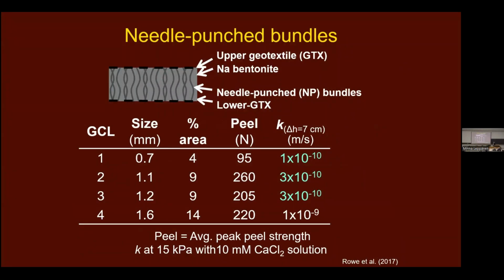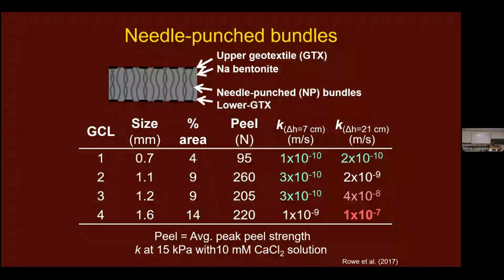Now, let's look at hydraulic conductivity, and you can see I've put 7 centimeters of head on it. Very low head, a small gradient, and you can see the first 3 are coming in around 1 to 3 times 10 to the minus 10, and number 4 is already about an order of magnitude higher than number 1. They're all bentonite. They've been exposed to exactly the same conditions. And already we see an order of magnitude difference in performance because of the initial conditions of the GCL.